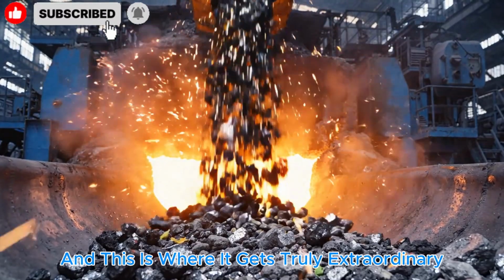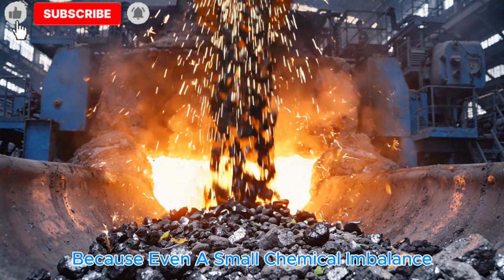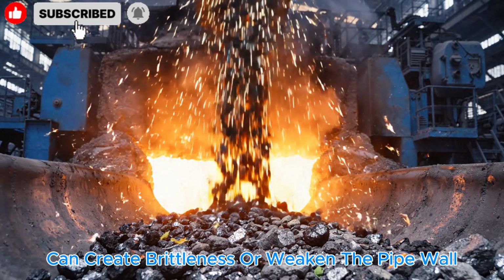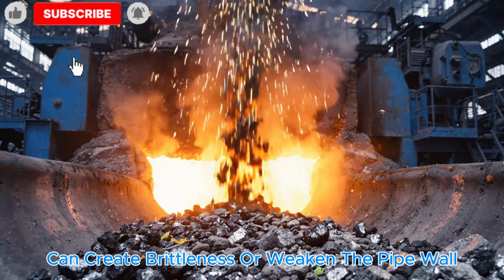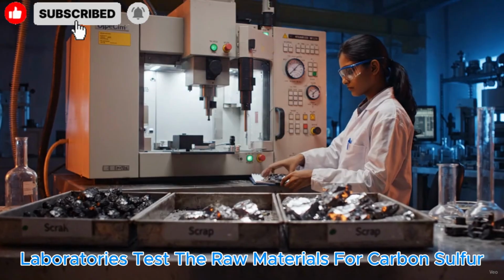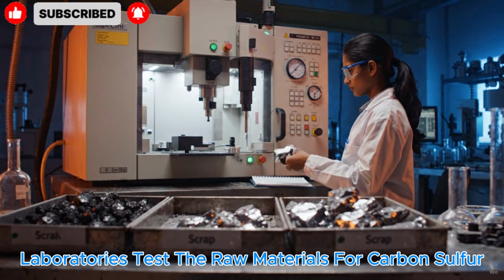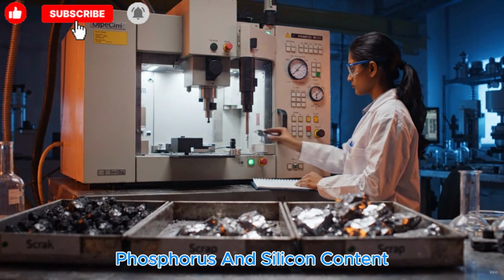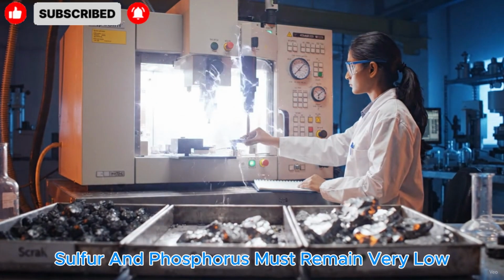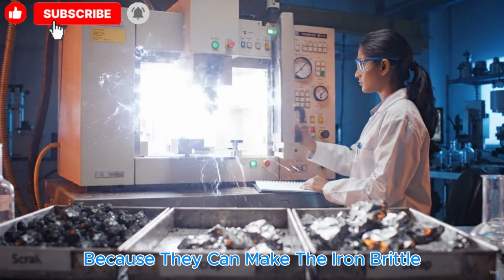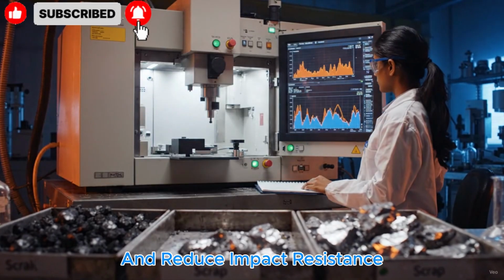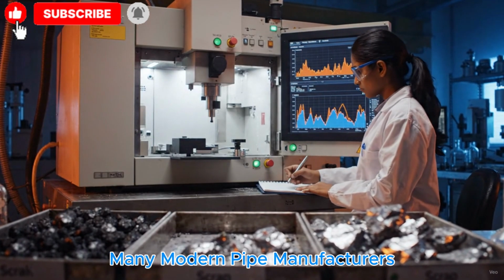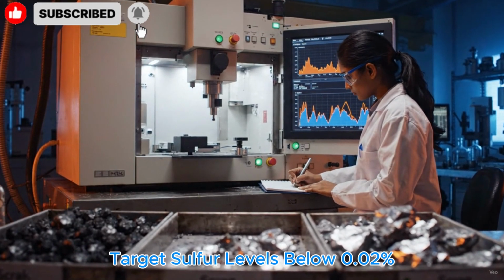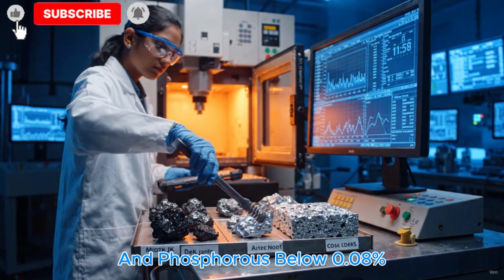And this is where it gets truly extraordinary, because even a small chemical imbalance can create brittleness or weaken the pipe wall. Before melting begins, laboratories test the raw materials for carbon, sulfur, phosphorus, and silicon content. Sulfur and phosphorus must remain very low because they can make the iron brittle and reduce impact resistance. Many modern pipe manufacturers target sulfur levels below 0.02% and phosphorus below 0.08%.